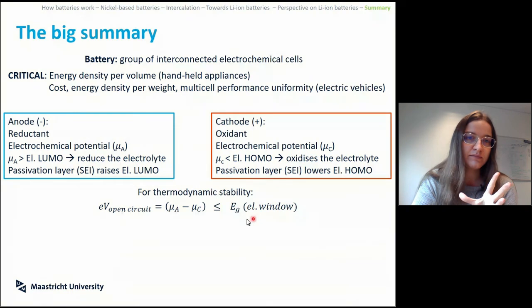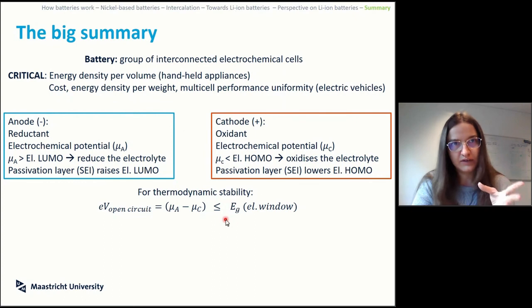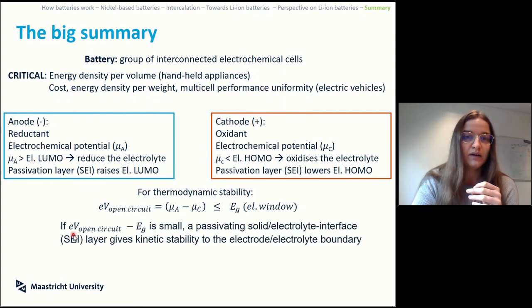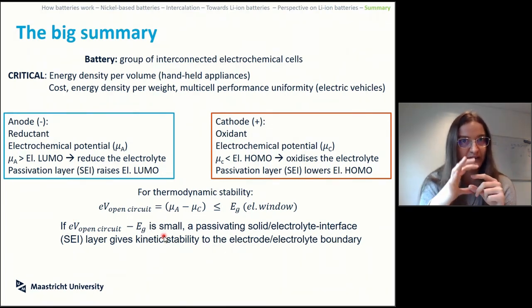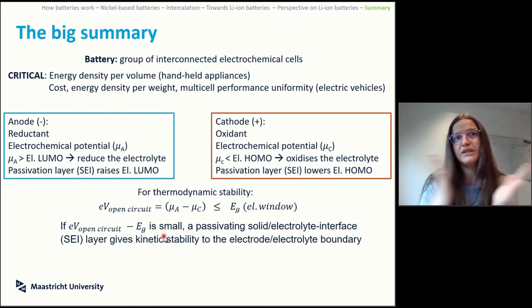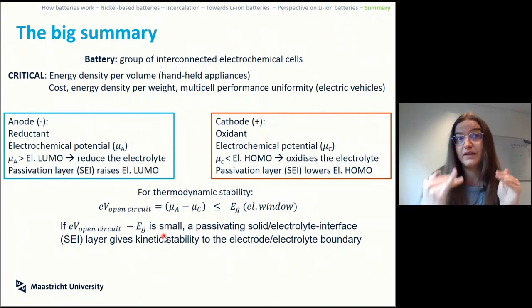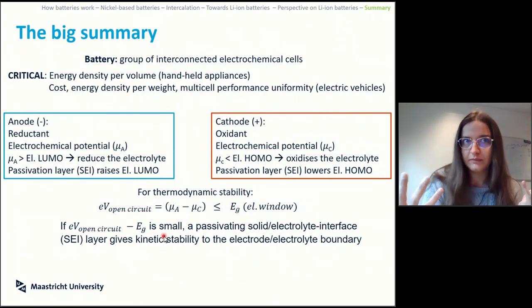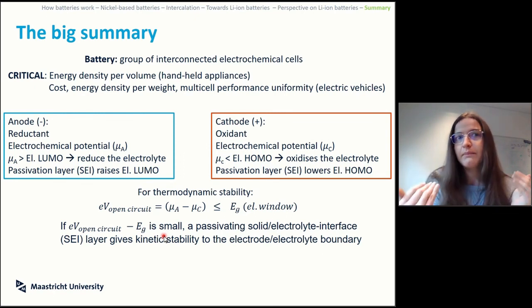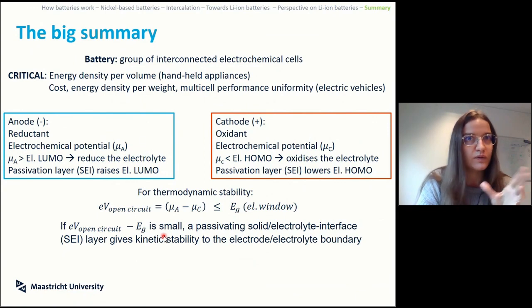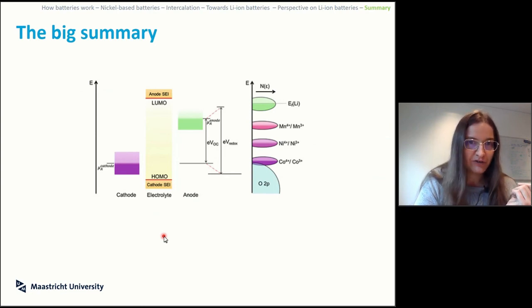For electrochemical stability, the voltage at open circuit needs to be the distance between anode and cathode, but it needs to be lower than the electrolyte window. Otherwise, you're doing electrochemistry on the electrolyte. If the difference between the window of anode and cathode and the window of the electrolyte is small, you can form these passivating layers on the two sides, which gives stability, so you don't keep doing electrochemistry on the electrolyte, but it can give some issues to how much lithium you are actually able to bring around. So, our nice arrangement of energy levels to remind ourselves of this thing.